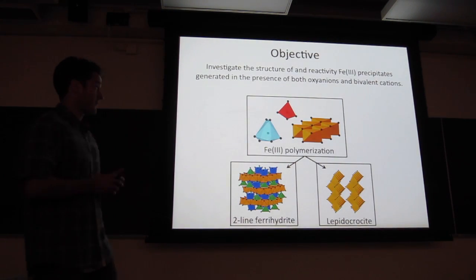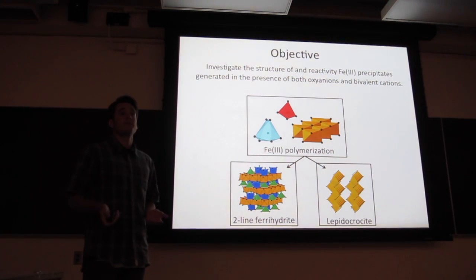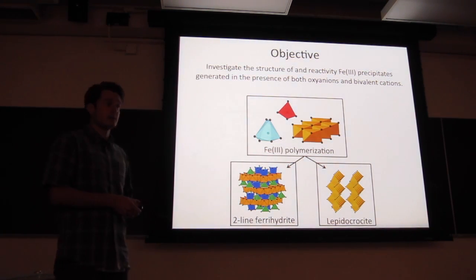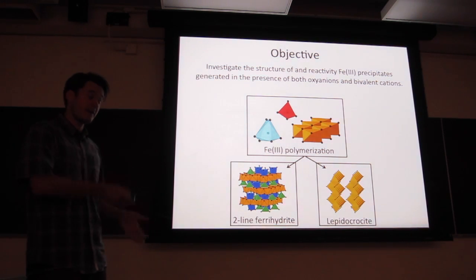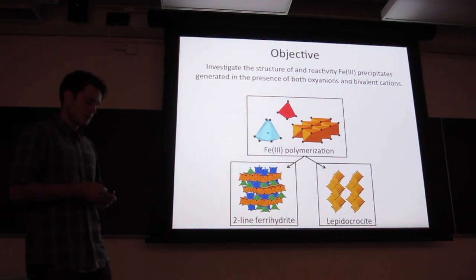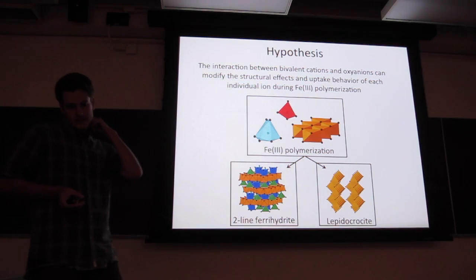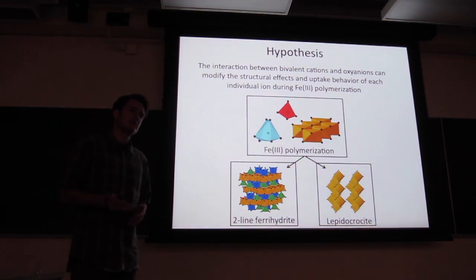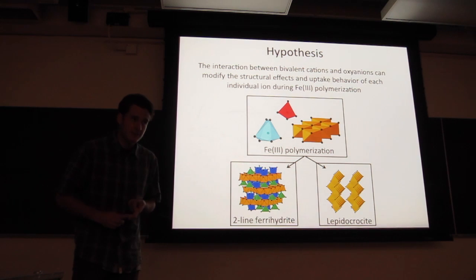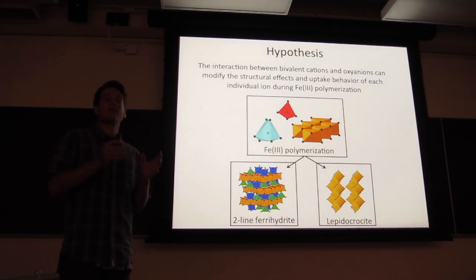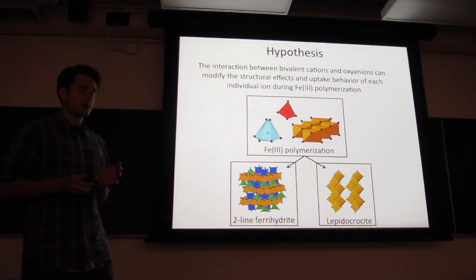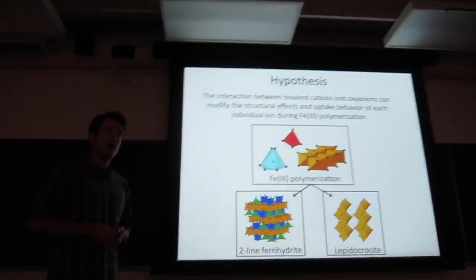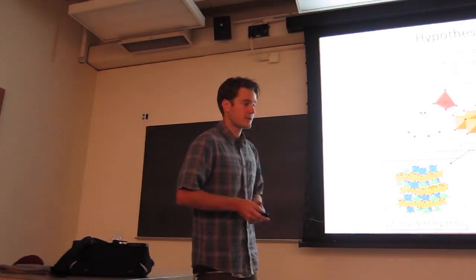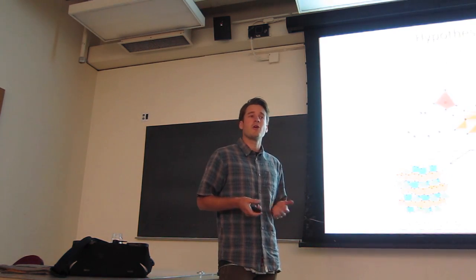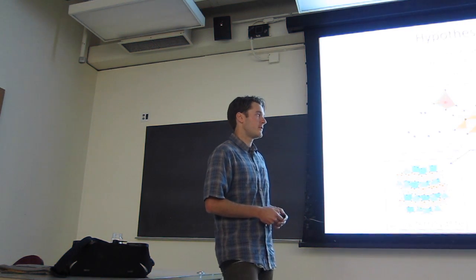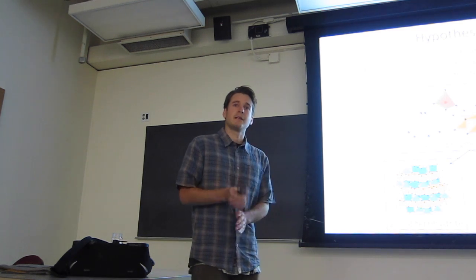Okay, so the objective for this work is to investigate the structure and reactivity of iron 3 precipitates generated by electrocoagulation in the presence of oxyanions and bivalent cations, and try to characterize that interaction. And what we expect to see is that relative to a single solute system, meaning a system that has just phosphate or just arsenate, when in combination with the bivalent cation, that's going to change the structural effects and the uptake behavior of the oxyanion. And so these combined electrolytes, you can call them binary electrolytes if you like, they're likely a more representative electrolyte than working in a single solute model system.